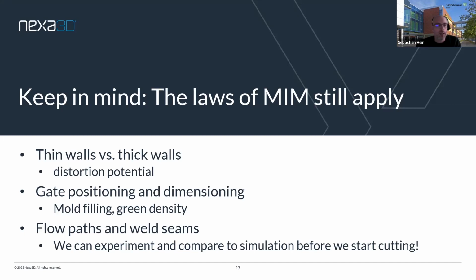So there are a lot of things that come into play, and this of course can also be supported by mold filling simulations that are state of the art, that you can use also to simulate the filling behavior of your printed mold if you are not sure how the flow fronts behave, for example, and how the flow path is. And if you want to avoid these weld seams, as they're named here, you can integrate also simulation for the mold filling. Next slide, please.